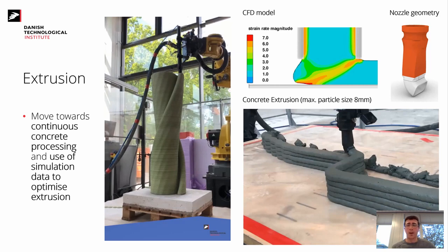And we managed to get an extrusion that is not rough, to the point that you start tearing your material, because it takes less shear to crack a mix. I mean, during extrusion, when you're using larger aggregates. So you would have to increase your volume of paste or amount of mortar in that mix design in order to make it smoother to mix. But instead of doing that, which would be opposed to a sustainability approach, we modified the nozzle geometry in order to reduce the shear strains during extrusion, and then accomplish still a successful print.